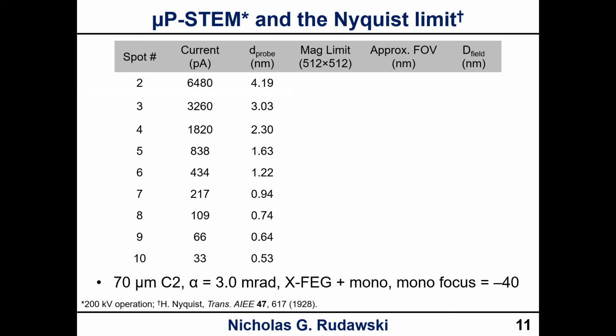So if we look at Microprobe-STEM and how this relates to the Nyquist limit, again, we're assuming these parameters here, our value for alpha, and this is what we have for our XFEG and monochromator. And we're again assuming 200 kilovolts, okay? So if we look at the different spot numbers here, those are the current values that we're getting. Then we can calculate the probe size, okay?